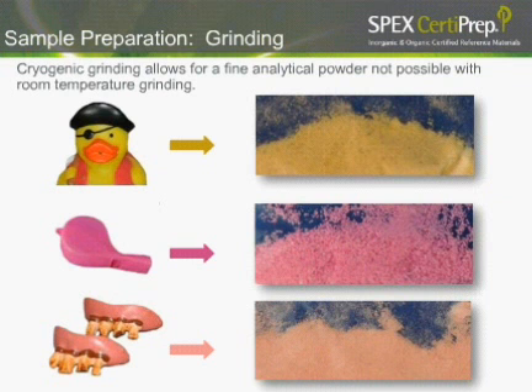So what we ended up with was this nice fine analytical powder. Something like the PVC duck was a very nice fine powder. Something like the whistle, which was a low-density polyethylene, was a little chunkier. That's a little harder to grind. So we got a very good result from our freezer mill.